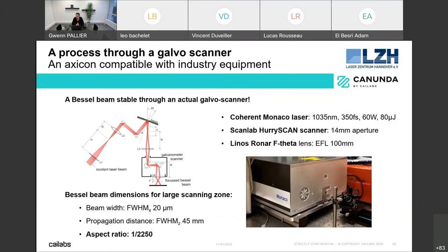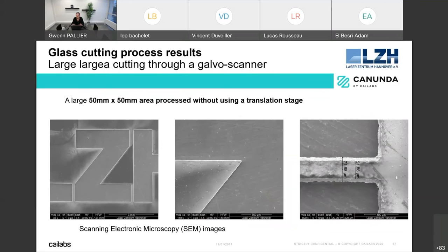So we want to do that using a reflective optic. We have developed a reflective axicon system, and we did this experiment with a Coherent Monaco laser, a scanner, and an F-theta lens. The results are just here. We were drilling the LZH and the Cailabs logo on a glass which is only 100 micrometers thick. It's a thin glass.